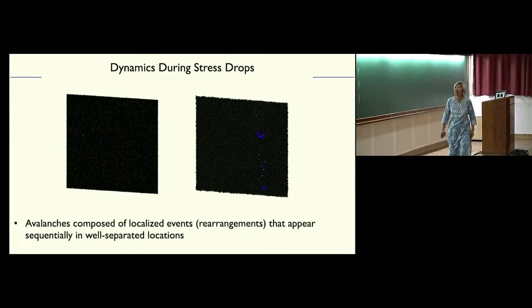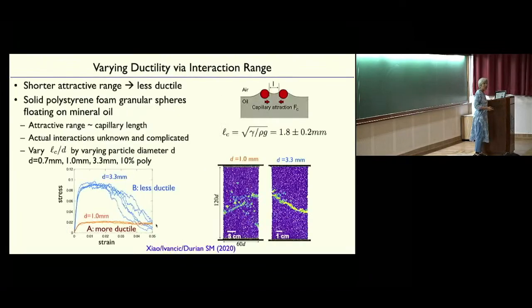I have a quick question about the right movie. So that one's less ductile. In the granular case, the larger particles were less ductile; the strain got more localized. So you cannot see, for example, crack nucleation. Doug, do you want to comment on fracture in your granular systems? I don't know if you want to call it fracture or not, but certainly the strain is localized. Yeah, it does eventually fracture. See the difference in the way the strain is spread out. In the case on the right, it will pull apart across the place where the strain is localized. But on the left, it'll flow and neck down and then pull apart. On the right, whether you call it fracture or not, it's definitely more brittle. Eventually it breaks apart, but it's not really snapping.